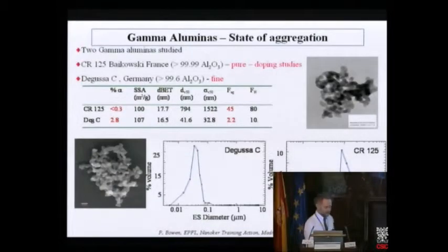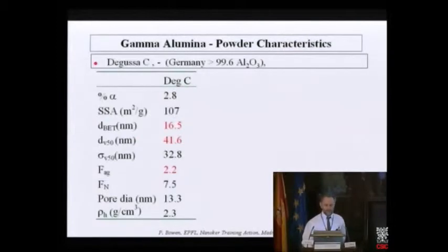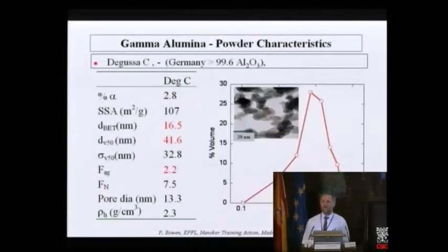So, if we take these, this is a size distribution, this is 1 micron, you can see that these particles are heavily aggregated. The Degussa C disperses quite well, most particles are below 100 nanometers. If you then plot the Degussa C, it seems quite nicely dispersed. But this aggregation factor is just an average, and at 2.2 it's still relatively aggregated.